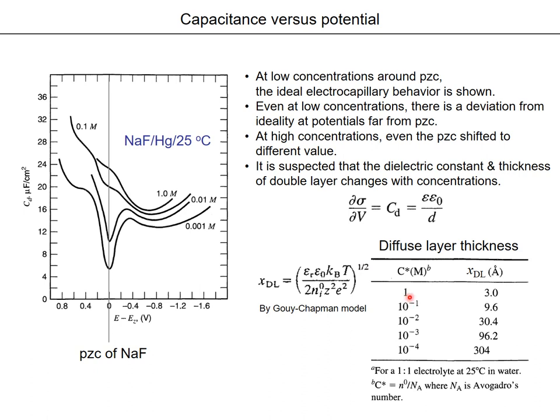So in this table, we have calculated the diffuse layer thickness as a function of concentration. At one molar, the thickness is just 3 angstrom. However, when we go to 10 to the minus 3 here, it is about 100 angstrom. Therefore, with the effects of concentration, the capacitance values, or the capacitance curve versus potential, could change. Anyway, at low concentration around the point of zero charge, you could get the ideal electrocapillary behavior.